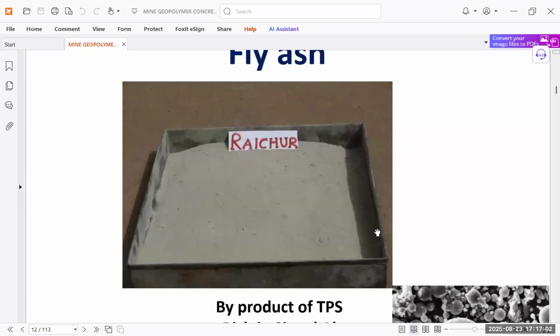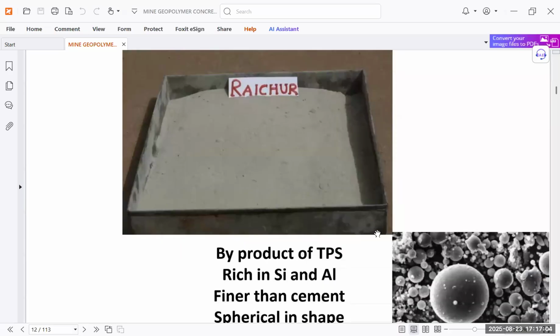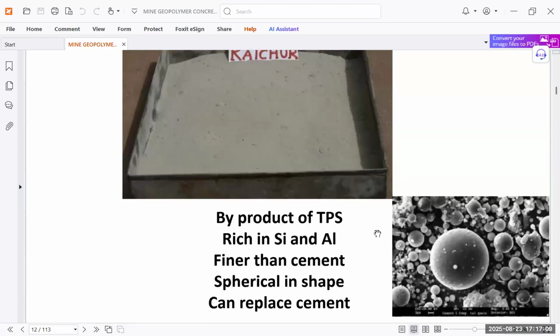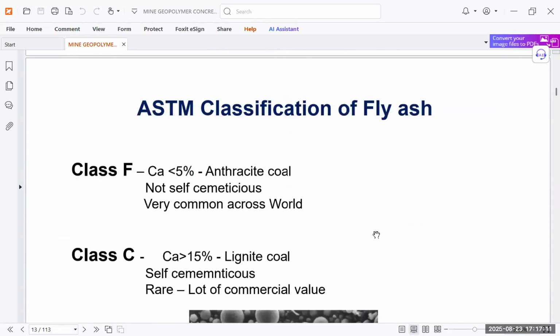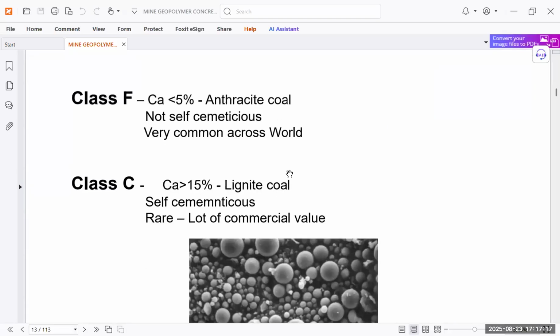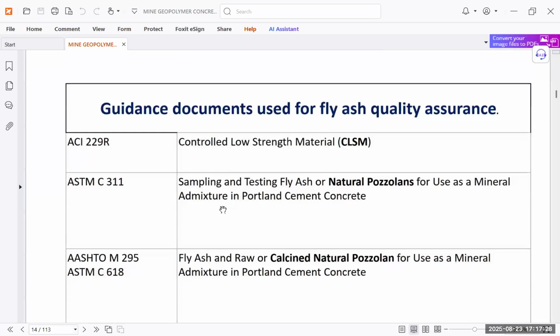Fly ash, as we already know, is a byproduct of thermal power stations, rich in silica and alumina, finer than cement, and spherical in shape. So this is also one part of this. Then the ASTM classification of fly ash: Class F has calcium less than 5%, comes from anthracite coal, is not self-cementitious, and is very common across the world. Class C has calcium greater than 15%, comes from lignite coal, is self-cementitious, and has a lot of commercial value. So we have some idea about fly ash.